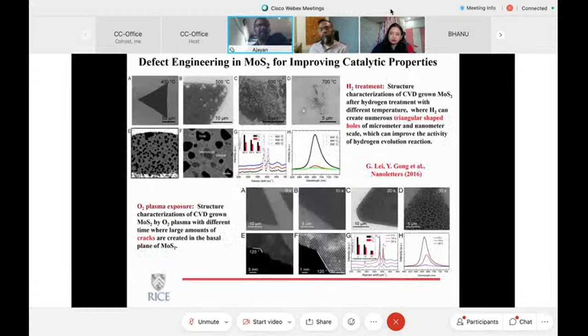And then some people have actually intentionally introduced defects by oxidation or hydrogenation processes. And these are done essentially to improve chemical reactivity or catalytic reactivity. So we have done some work where exposure creates these specific holes in the structure, exposing more edges, edge atoms. And that increases the catalytic activity in hydrogen evolution reactions or similar reactions. So again, these materials like molybdenum sulfide have traditionally been used as a catalyst, but not pure molybdenum sulfide, rather doped molybdenum sulfides. And here we were trying to understand how things like dopants and defects change the chemical activity.